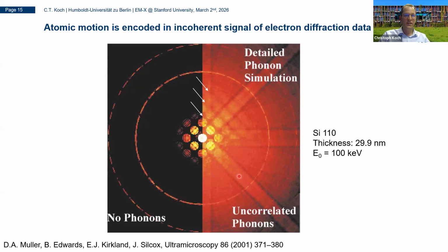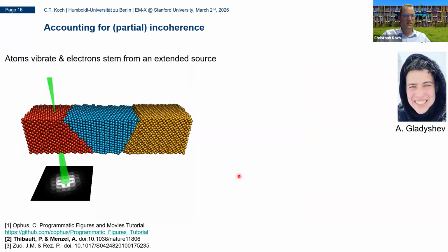And the question is, is this also then recoverable in ptychography? The question, of course, has an answer, and I wouldn't talk about it if the answer wasn't yes, or at least you can make an impression yourself if you look at these slides. So to simulate these thermal diffuse scattering patterns that I showed on the previous slide, what you do is you shake the atoms and you produce a diffraction pattern for each displaced configuration of atoms. And if you want to do it right, you also move the beam a little bit and convolve the diffraction patterns in real space to account for the effect of partial spatial coherence, because we always have partial spatial coherence in our experimental data.